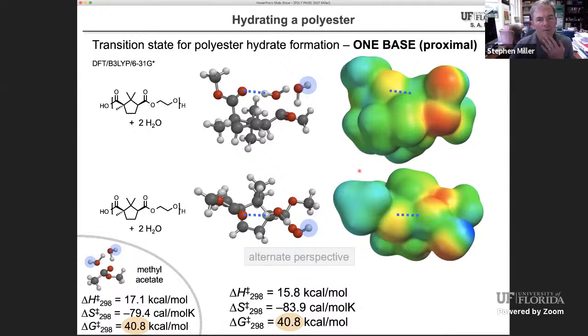So what about our polymer? Well, our polymer is not methyl acetate. If you look at it, it's a polymer that's really one molecule with a whole bunch of bases in it. So you've got lone pairs everywhere. Every ester group has lone pairs, which can conceptually function as a base, maybe in a base catalyzed process. So this first transition state shows the approach of one proximal base coming up to this water molecule and taking away that large positive charge that otherwise would tend to build up at this hydrogen. So that positive charge is delocalized by the carbonyl oxygen of a nearby ester group.